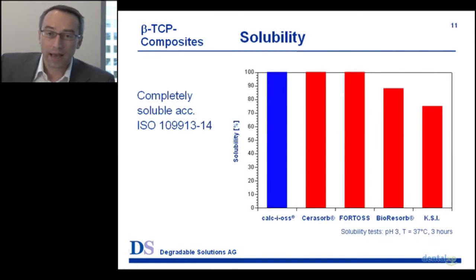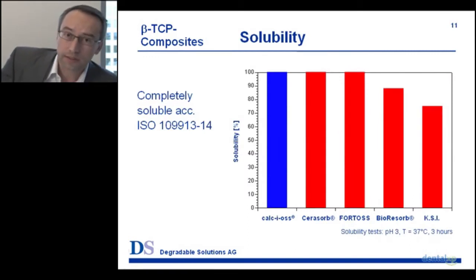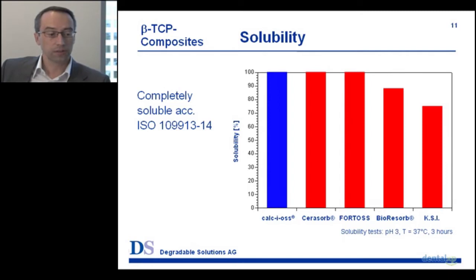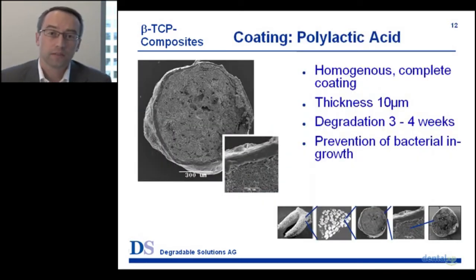We went into an ISO standard dissolving test. As you can see here, the blue bar is the granules we developed, and you can see they passed this test at 100% solubility after 3 hours in this pH 3 citric acid solution, which mimics the activity of the macrophages in the body.